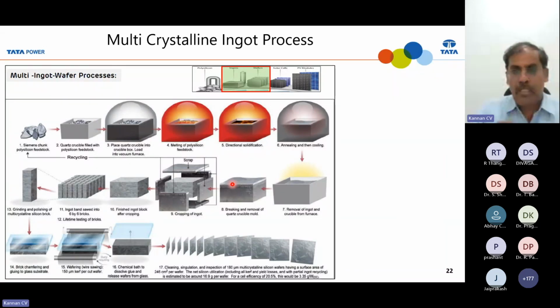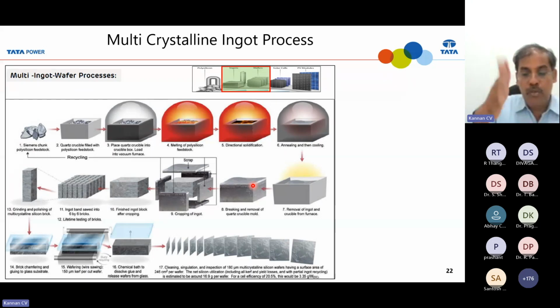So this is the process. After you convert into a solid piece, then you take out the crucible. Then the crucible will be like this. It's a square shape with a 30 centimeter or 40 centimeter height, with a 1.1 meter or 1.5 meter width. Then you just take out the edges, because as I said, the crucible is in contact with this one, so a lot of contamination. You have to remove those low quality areas, slice it, then you will get a very good area here.